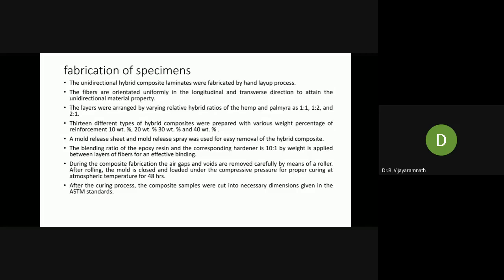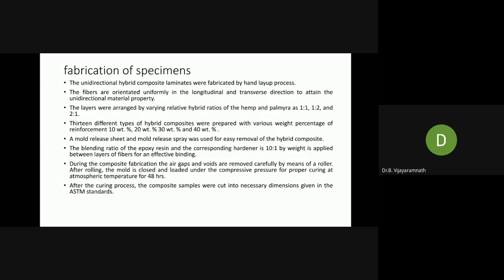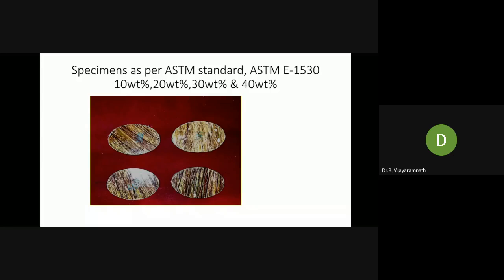In order to conduct the thermal conductivity test, we prepared specimens as per the standard ASTM E1530, circular disc type specimens, which are tested on a thermal machine that provides the value of the thermal conductivity. So here you can observe the specimen preparation.